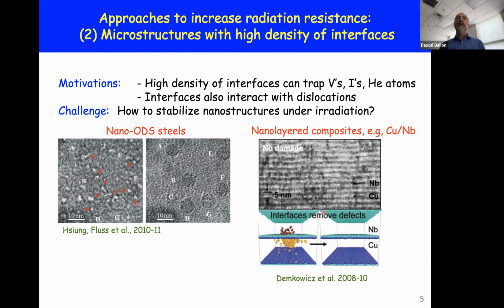And thanks to the very high number density of interfaces, when you have a displacement cascade here, close to a copper niobium interface, you may resolve or eliminate all the damage right away and not have to worry about its accumulation over time. One of the challenges, however, with these nanostructured materials is that nanostructures tend to be prone to coarsening, especially at elevated temperature and possibly under radiating conditions.